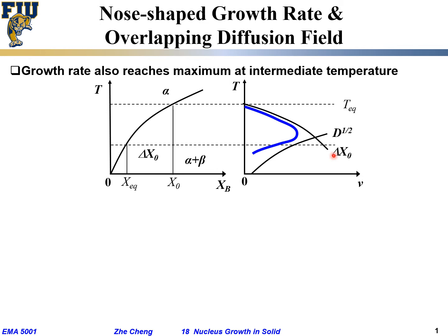The whole thing would be enveloped between these two effects. There will be a compromise between supersaturation and diffusion. When I am close to equilibrium temperature, my growth rate is low because although diffusion is fast, I don't have enough supersaturation. I don't have much driving force. As a result, it doesn't grow very fast.